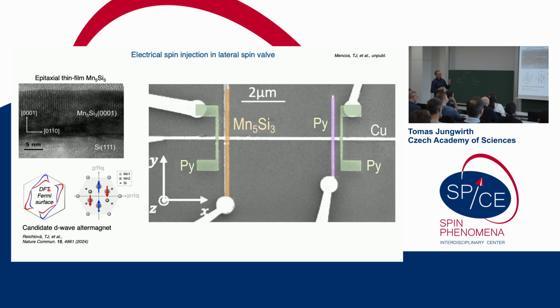So our colleagues said, okay, we're going to try to see if this compensated magnet can generate spin polarized electrical current. Now, what we've seen before, when I showed you the device which is already in integrated circuits, is the spin valve or magnetic tunnel junction. Here you have the two magnetic electrodes which are separated by just a nanometer, sometimes even a fraction of a nanometer. So the injecting electrode, the detecting electrode, and also the transport channel are virtually in the same place. So these are sort of local devices.